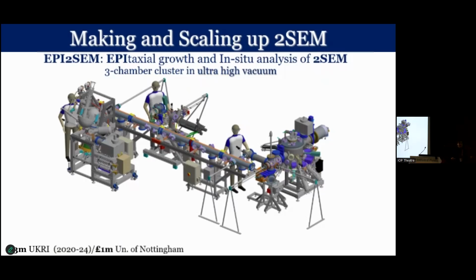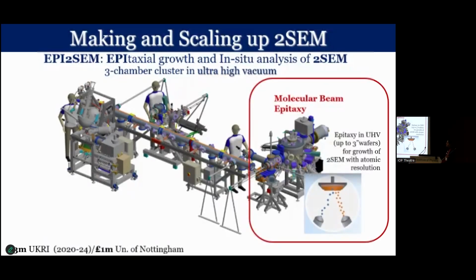So we came up with this idea of a new facility that we call EPI2SEM, that stands for epitaxial growth and in situ study of two-dimensional systems. So you can see it is a 3-chamber cluster in ultra high vacuum. So it's quite complex system. We have a first chamber. When I say UHV, ultra high vacuum, it means 10 to the minus 10 millibar. So we really need to have a high purity environment to grow or to develop this system. And also with the atomic resolution.